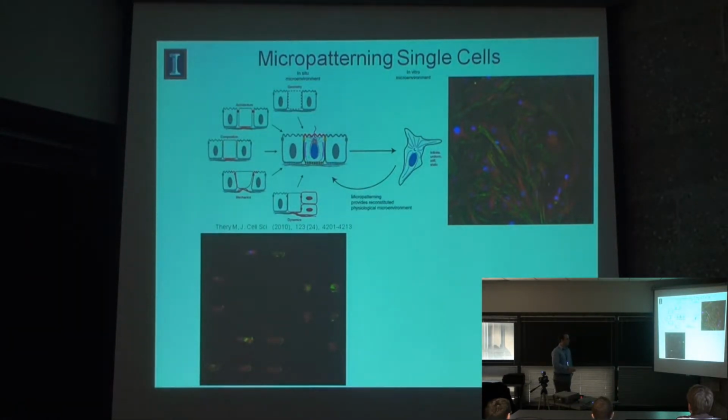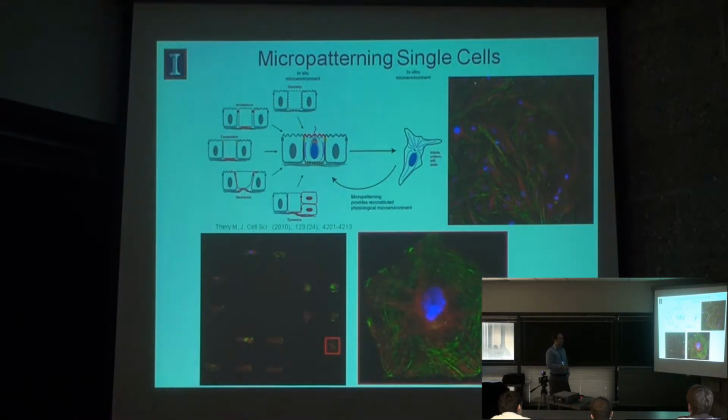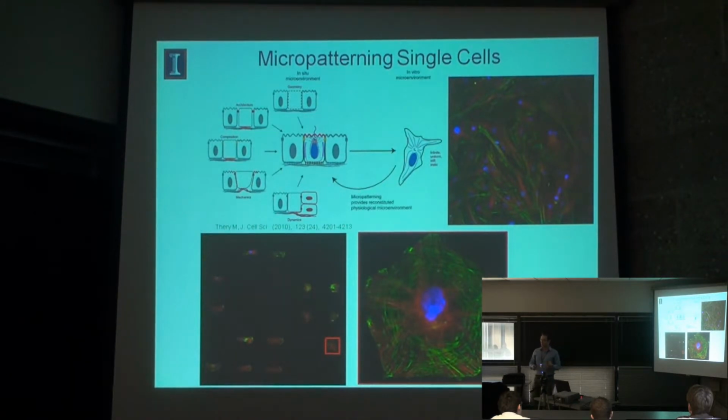And so here's a picture of cells that have been micropatterned in our lab in a range of different geometries. And the reason we do this is now, instead of just changing area, we manipulate some of the subcellular curvatures and aspect ratios and things like that. And we can get very different organization of the filaments within the cells. So this is a flower shape. And you see here we got the nuclei in the center, and we get this nice ring-like filamentous actin network. And it's just this beautiful web formation of microtubules throughout the cell. And by modulating that architecture, changing it up, using different shapes, you can influence the way that these things align, and use this as a method to study the importance of geometry and how it influences the cytoskeletal architecture.